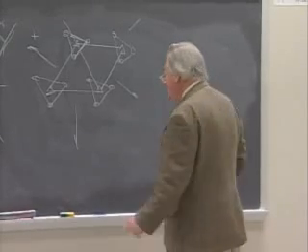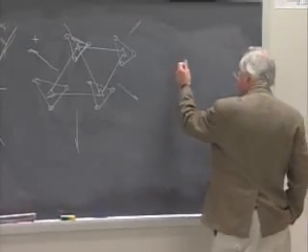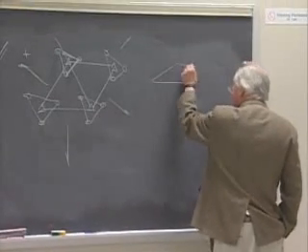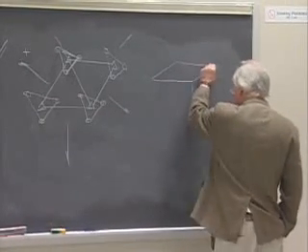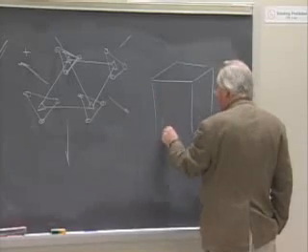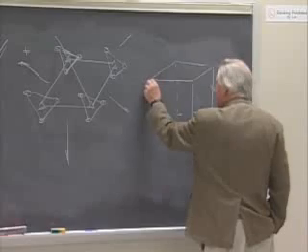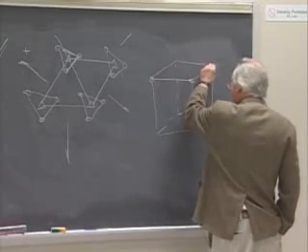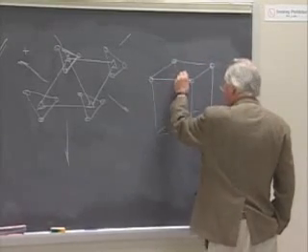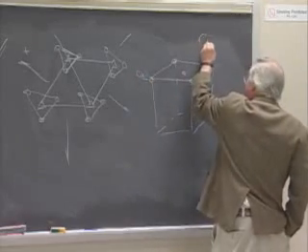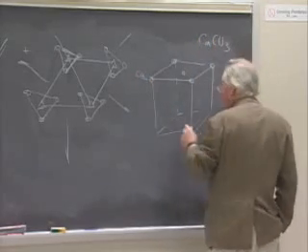There's another example of a material which again has a negative thermal expansion in one direction, and this is calcium carbonate, which is a complicated hexagonal structure, but it looks very, very much like the structure of rock salt in a distorted form. These are the calcium atoms, and calcite is CaCO3.